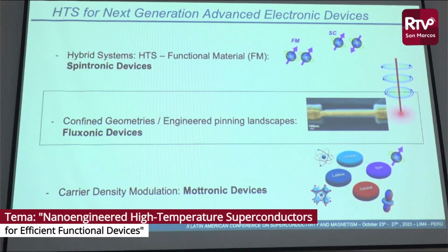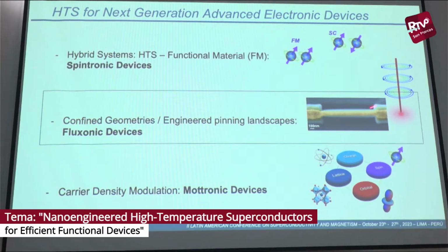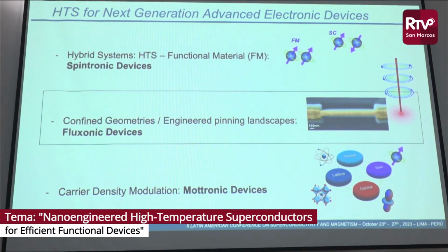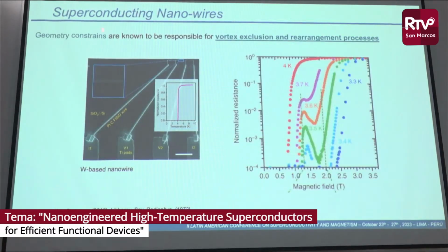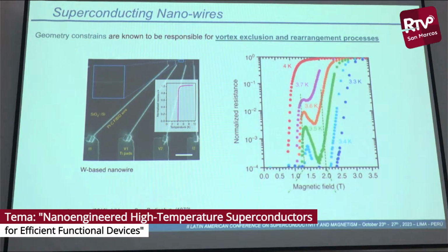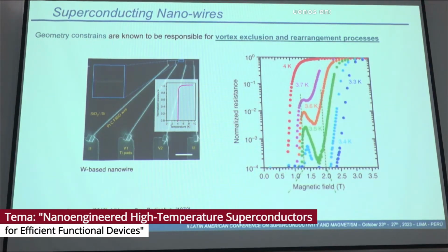Now, I go to the other structures, the other systems, in which we use the geometry of the material in order to try to play with the vortices in the system. And in this case, we are exploring superconducting nanowires. Since a nanowire has a size which is of the order of the key parameters of a superconductor, the coherence length and the penetration depth, several funny things can happen inside a superconducting nanowire, like different reentrants of